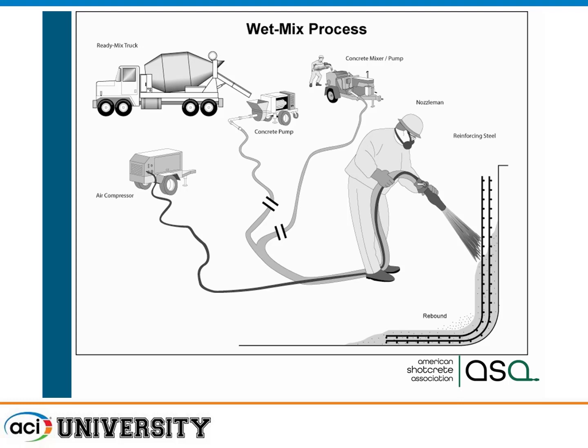Then we add air at the nozzle to accelerate it to that 60 to 80 miles per hour. So the fundamental difference: dry mix, we're adding water at the nozzle. Wet mix, we add air at the nozzle. Because in dry mix, we are conveying all the materials through the hose, we tend to use a bigger air compressor. So if you're on a project using dry mix, it will generally have a larger air compressor than what you would see in a wet mix application.